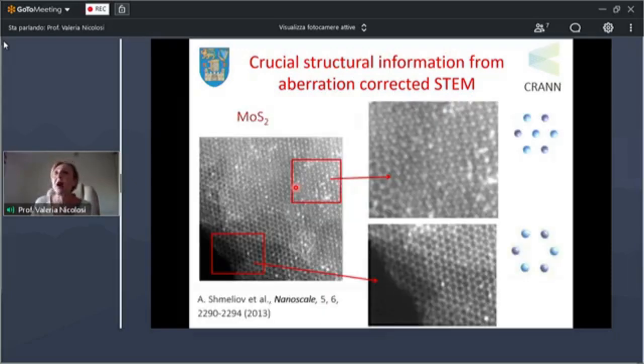This is an example of molybdenum disulfide nanosheets. We saw in this work that the sheet was actually made of a variety of different steps of different thicknesses. Here was a thicker part. Here you had few layers. Here is a monolayer area. But importantly, we also understood that by liquid phase exfoliation, we formed sheets that were not absolutely homogeneous.